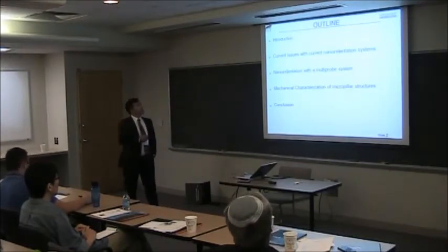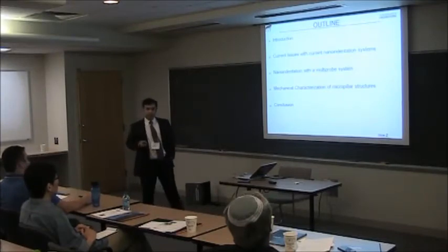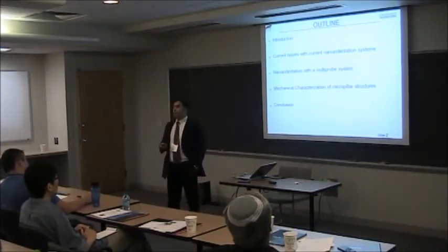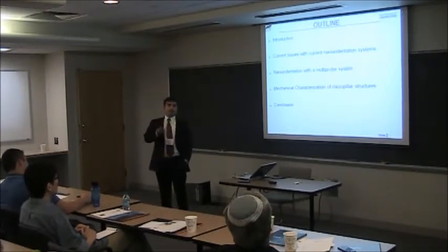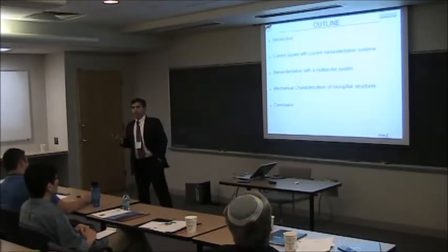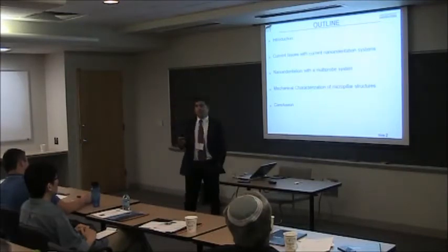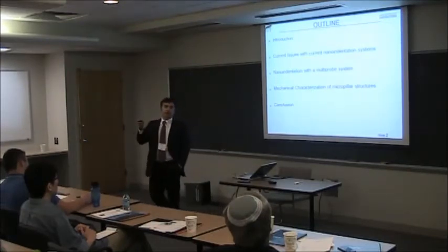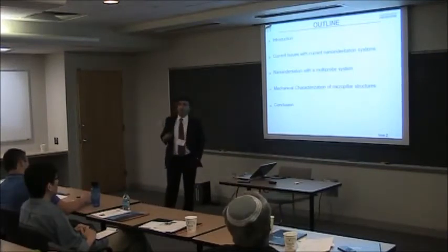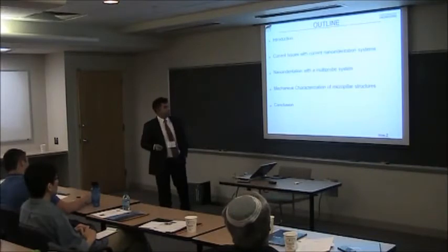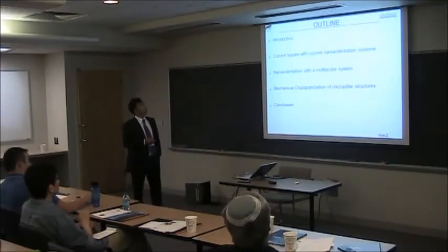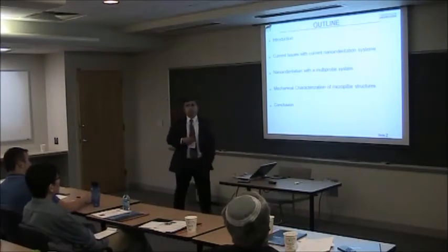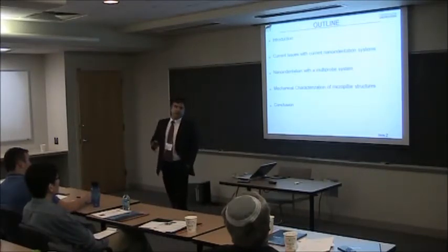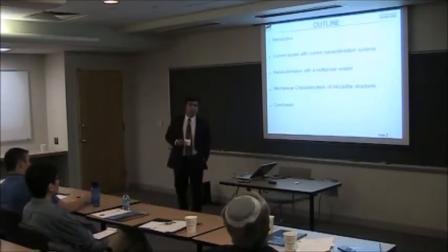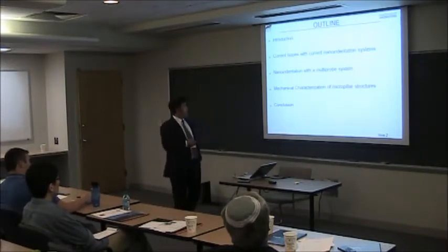For that, we say, okay, I need to know the Young's modulus of the PDMS so that I can look at the deflection of the PDMS pillar and I can calculate the force. But the Young's modulus of PDMS in pillar format, with a high aspect ratio, in fact what we believe, will be different than the bulk parameter Young's modulus. So that's why we want to measure that through nanoindentation. And regular nanoindentation tools, as Aaron was saying, AFM cantilevers are used. There are so many problems with them, so we had this tool in-house at RIT, and we wanted to make use of it so that we can actually do a better characterization.